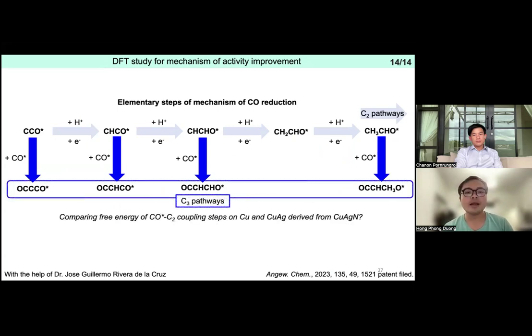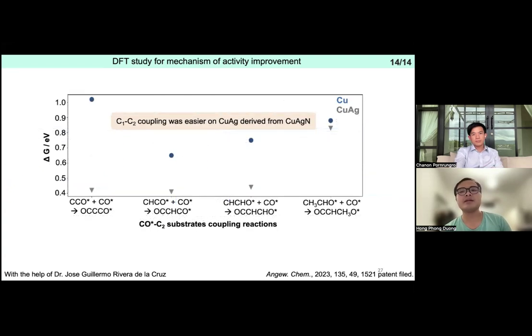And the thing he did was compare the free energy of those reactions over the surface of bare copper, and also silver-copper or silver-gold-copper derived from the nitride material. He found that in all cases it's actually easier with the metal doping compared to the bare surface of copper. And this result is also very consistent with the previous literature.